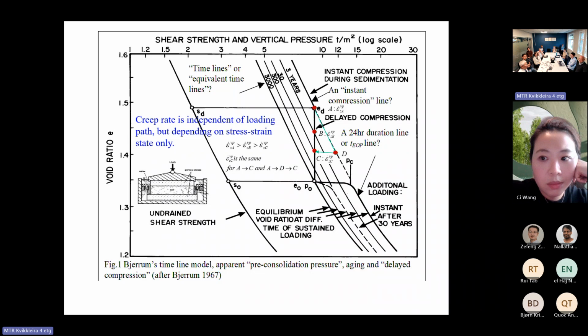Should it be the same? Same as you say there. Yeah. So we found all these creep lines by having one test creeping for 1 year. Then we started at the same point, doing different unloading to different levels, and then measuring the strain rate at the different amounts of unloading. Yeah, good idea. In addition, we had an oedometer curve, and also the triaxial test, to measure the non-linearities. So this lambda value that you say is not linear, we also found the non-linearity of that, and looked into this kappa value at different unloading steps. So we were finding all the parameters and wanted to see whether this fits together.